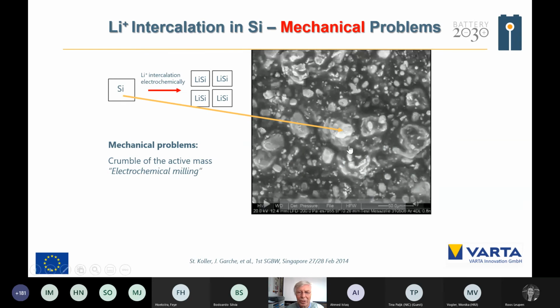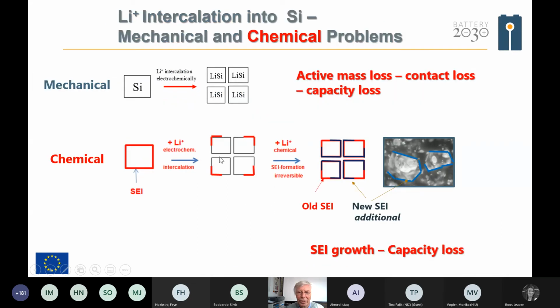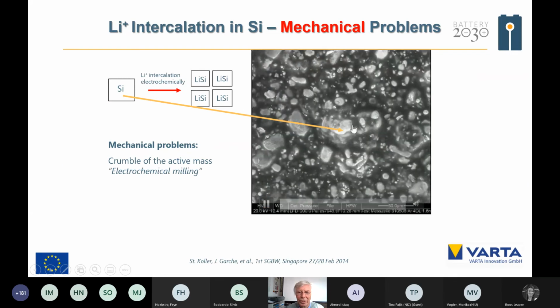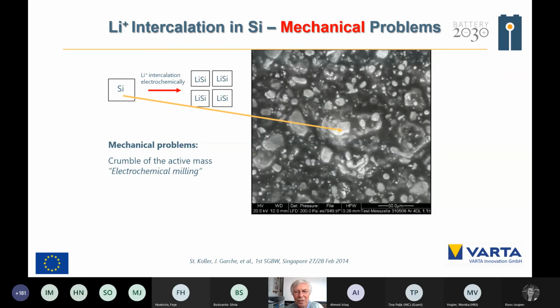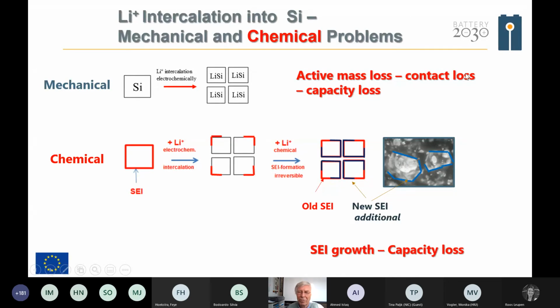That is an example for the lithiation of silicon. What you see here is silicon. Yeah, you can see the lithiation of the silicon, the increase of the volume, and that will bring you a higher volume and mechanical problems. And besides these mechanical problems, which lead to contact losses and capacity loss, you also have chemical problems because you create a new surface which is not covered with the SEI. So after the charge of the silicon you have to form a new SEI, and the new SEI means again capacity loss.